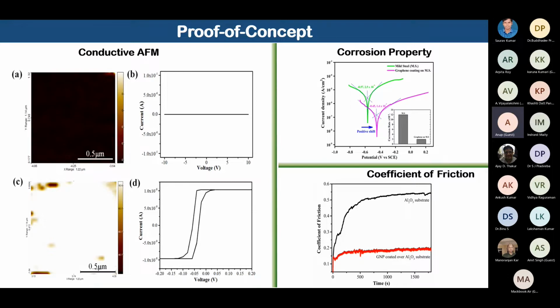But here, the same alumina we coated with the graphene coating, and you can see that for a small range of the voltage, the current has shot up like anything and has reached saturation. So this is showing that definitely the graphene coating has been intact, because we know that the electrical conductivity of the graphene coating is very high.